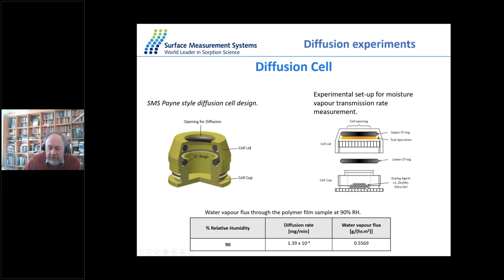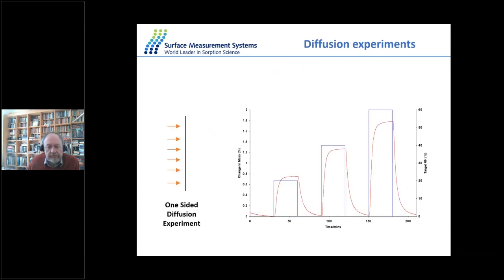And underneath the sample inside here, we're going to have a zeolite or an activated carbon. That's going to act as a drying agent. So up here, we're going to introduce some humidity. We've got our test specimen here, and we're going to get water vapor coming through the sample into here, and we're going to measure that in our machine. So this gets attached to the DVS machine, and we can measure the diffusion rate through this film in quite a nice little experiment.